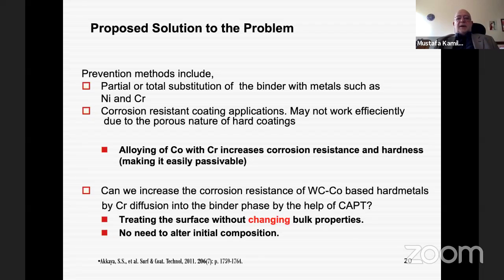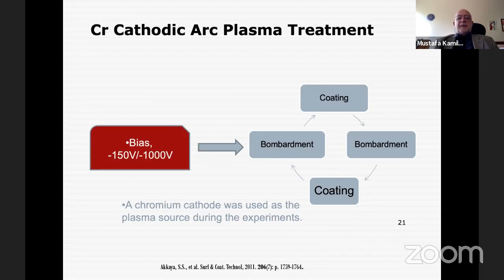But cobalt is a very easy binder to be used in the tungsten carbide cobalt system, and the technology is very, very well established. So we said, okay, let's again have a cobalt binder tungsten carbide cobalt sample, but let's try to alloy this cobalt binder phase by the method that we are proposing. That means we deposit chromium on it, increase the temperature of the substrate so that an alloying between cobalt and chromium takes place. So for that, we designed an experiment.